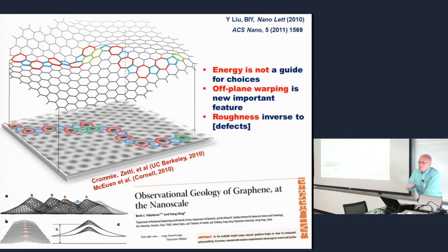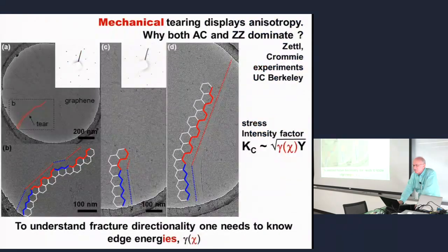Another important consequence is that in principle, at least a freestanding membrane becomes highly corrugated. You have these landscapes caused by these topological defects. So there is this interesting interconnection between topology of defects in the lattice and topography of what your system looks like. Now we look at the reverse situation. Can you have a topographically curved substrate and intentionally create some architectures and defects? But I will not talk about it.